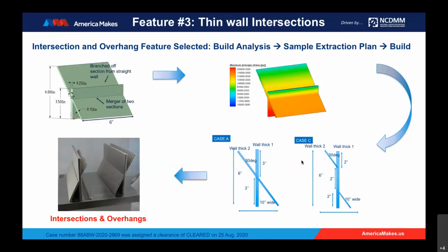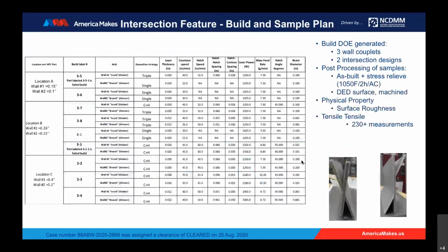So similar to the whole feature, we've designed the intersection wall geometry, followed that up with simulation to make sure it fits our conditions. Then we move to the specimen extraction plan and then proceed to fabricate it. Next slide, please. So here in this table, you have the different process conditions used to fabricate these walls. So we modeled the matrix based on the thickness or the exact feature that was in the high pressure case. So we matched up the thicknesses in three different locations of the high pressure case and tried to build our experiment around it. Next slide, please.